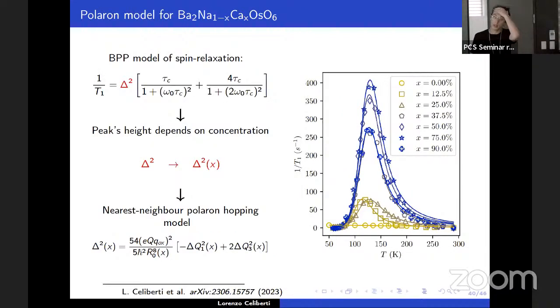So, when we rederive this model for the transition rate of the relaxation time, we obtain this formula for the parameter delta squared, which depends on the fluctuation of the Jahn-Teller distortion of the osmium oxygen octahedron. In particular, if you consider only nearest neighbor hopping, and also the fact that in all our calculations all other modes were negligible, we get this expression where you have only the breathing mode, which is kind of natural because when putting one more charge, your octahedron has to expand to accommodate this charge. And you also have this tetragonal distortion related, as we will see, to the Jahn-Teller distortion.